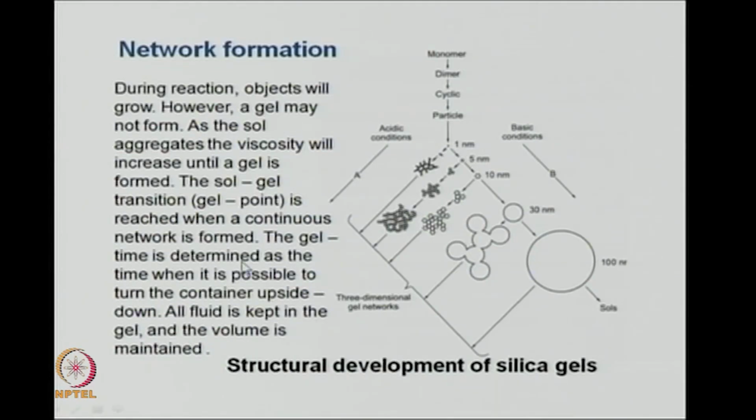The gel time is determined as the time it takes, after forming the sol, before the gel is formed. Now, how do you know when the gel is formed? It is very simple. If you take a sol and turn the container upside down and the fluid does not flow, that is when the gel has formed.